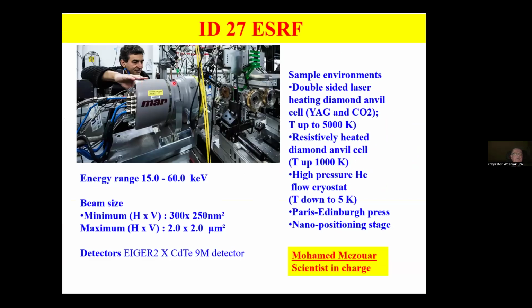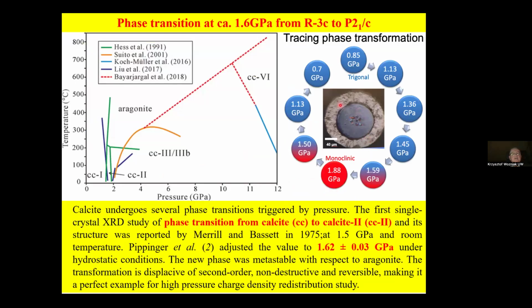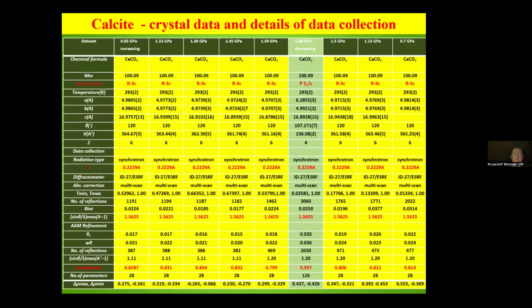Anyway, the data were collected at ID27 at the ESRF. It's an extremely good station, very well equipped, extra stabilized, with an Eiger cadmium telluride detector, and is run by Mohamed Mezouar. One can really focus the X-ray beam to, say, less than 2 micrometers, which is very helpful because one can collect separate data sets from single crystals. You can see a photo of the diamond anvil cell and a small tiny crystal of, say, 20 microns inside. And we've got very good quality data.